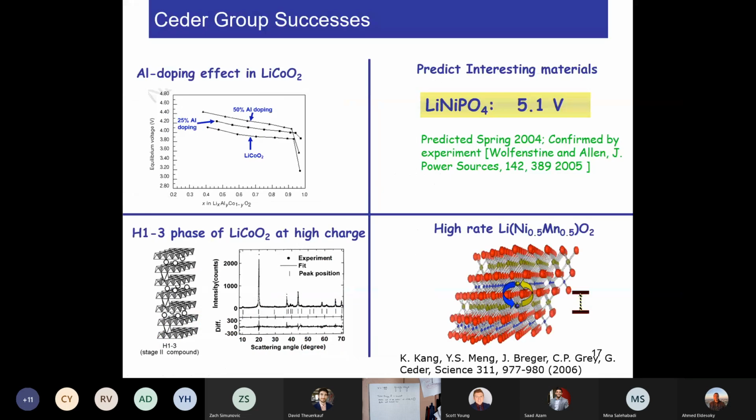Hi, Jeff. Yeah. So for this slide, normally during the Tesla conference call, when you were talking about the results from the cathode group, you often say like lithium in the nickel layer. Is this a similar thing? Like the nickel goes into the lithium layer and slows down the diffusion of lithium? Yeah, when the nickel goes into the lithium layer, it slows down diffusion. That's correct. So that's common for not just these materials, but for other NMC materials, right?